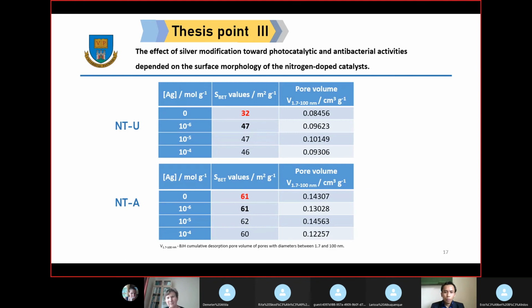It can also be seen in the specific surface area: for the N-TiO2 catalyst, the specific surface area increased after silver modification. However, for the NTA it hardly changed, remaining relatively stable even after modification. This is probably because on the non-hollow structure of the N-TiO2, the silver nanoparticles attached on the surface of the catalyst with a smaller size, but for the NTA, the silver nanoparticles agglomerated with a higher size and also attached inside the hollow structure.